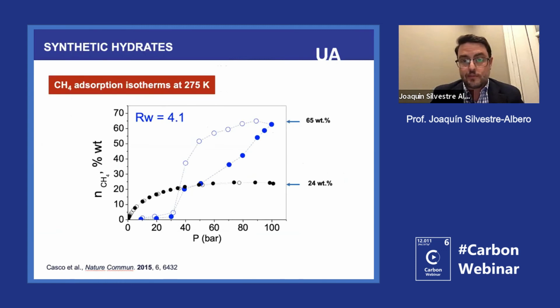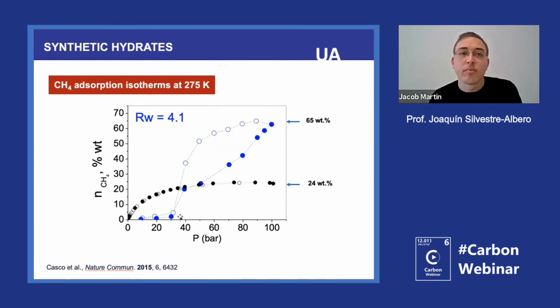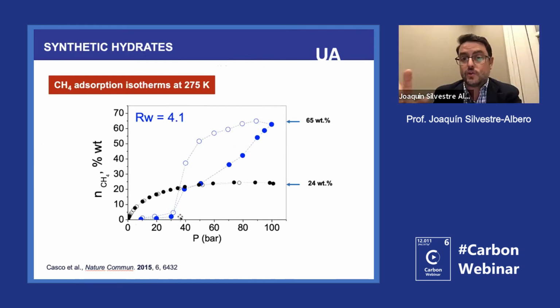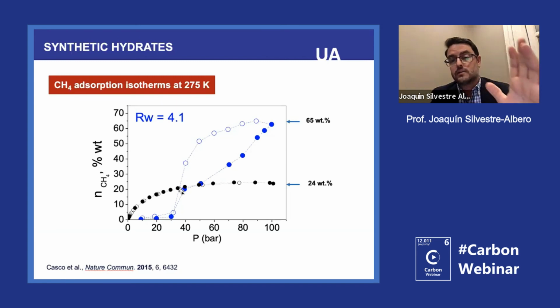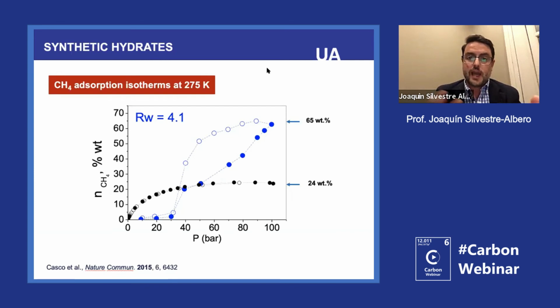After many years working with this system, we are quite sure that at the beginning, you have the blocking of the porosity because of the water present. Whatever is happening between 30 and 40 bars is external surface. So you are making hydrates in big cavities or in the external surface of the carbon. And whatever is happening above 40 bars until 100, this is something that is very slow. And in our opinion, this is all mesoporosity and microporosity. That's why you need higher pressures to reach these inner cavities and to promote the hydrate formation there.